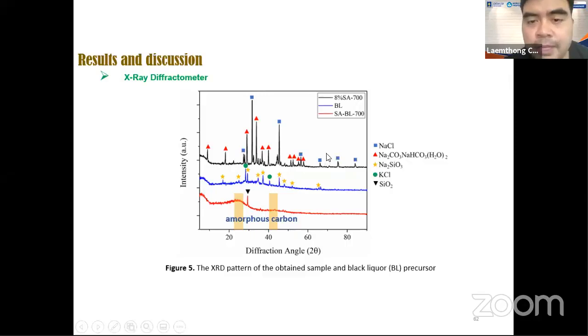And then we determine by using XRD, and we see that, okay, we can actually produce the amorphous carbon in our product. Our product is represented by the red line. You can still see sodium chloride and other sodium species that come from the black liquor, but afterward we can wash them out. So it's no problem in this case.